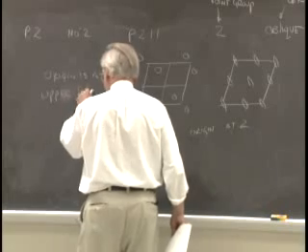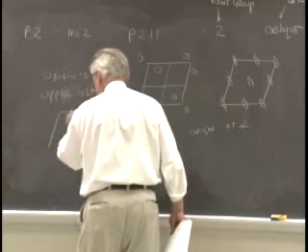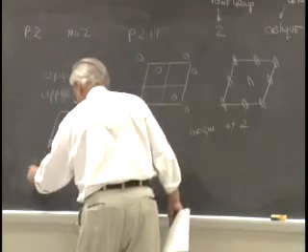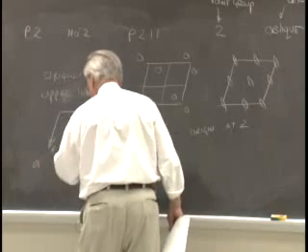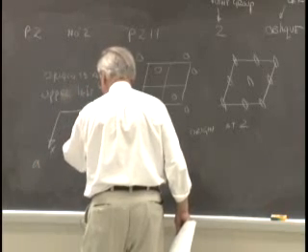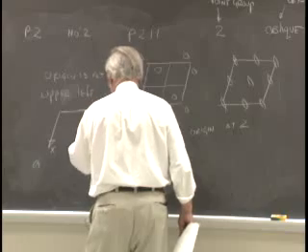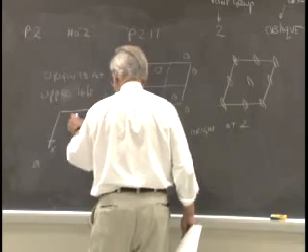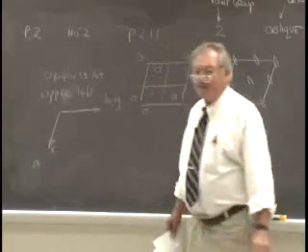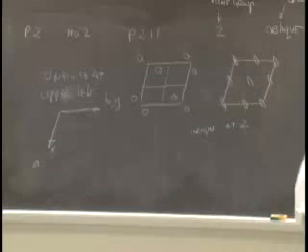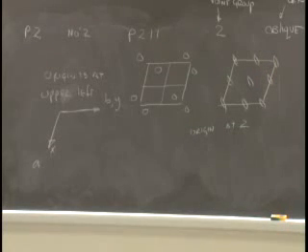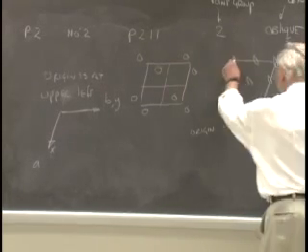And what is also assumed but never stated is that the x-coordinate in the a-axis goes down and the y-coordinate in the b-axis goes from upper left to the right. That is nowhere stated anywhere in the international tables, but that is the direction that is assumed for the reference axes. Okay, so we'll take our origin at the twofold axis.